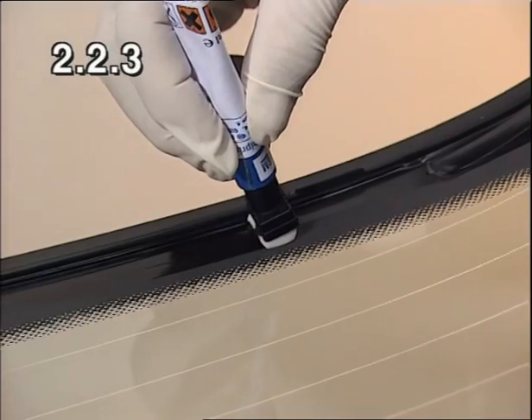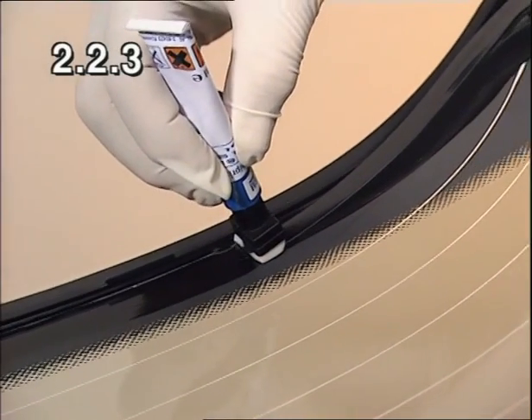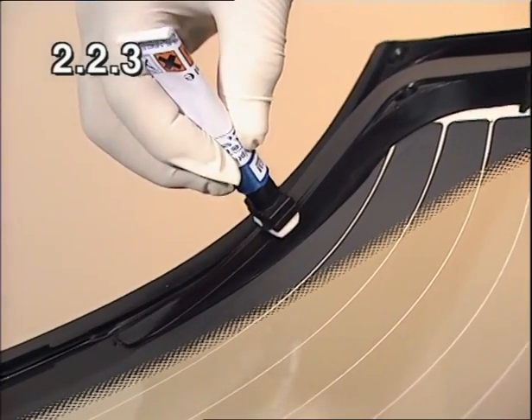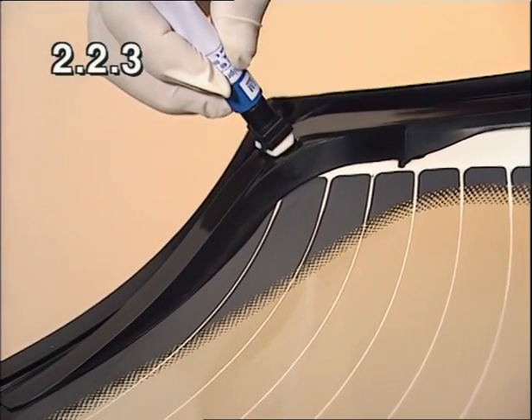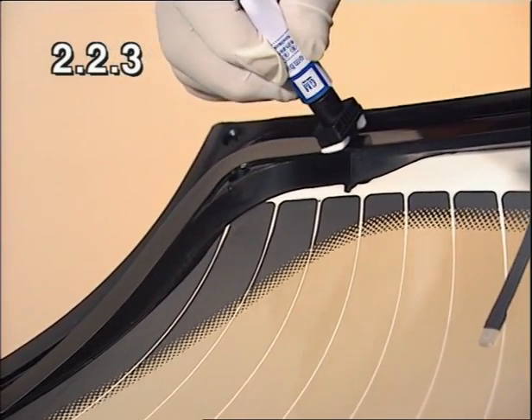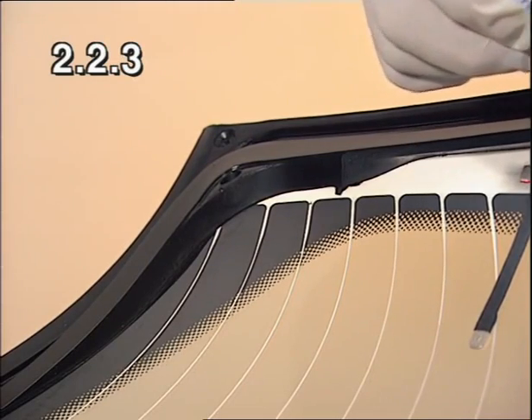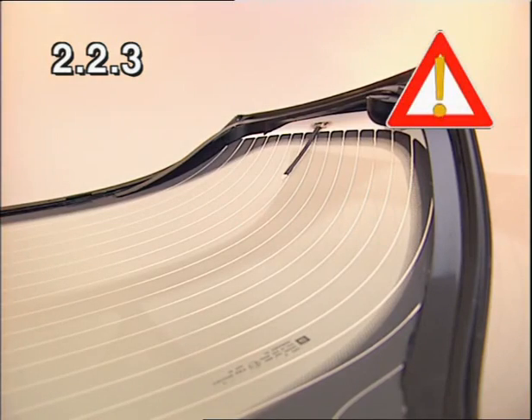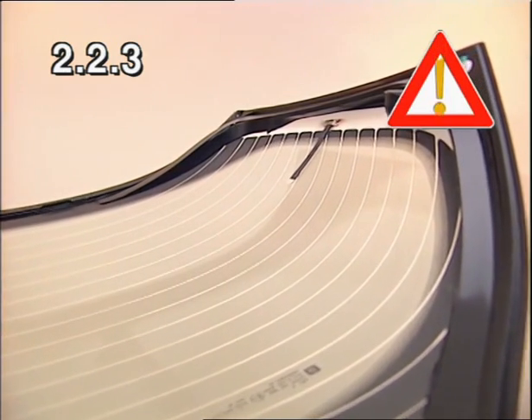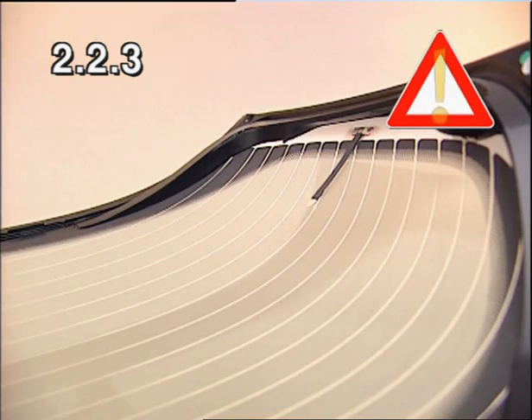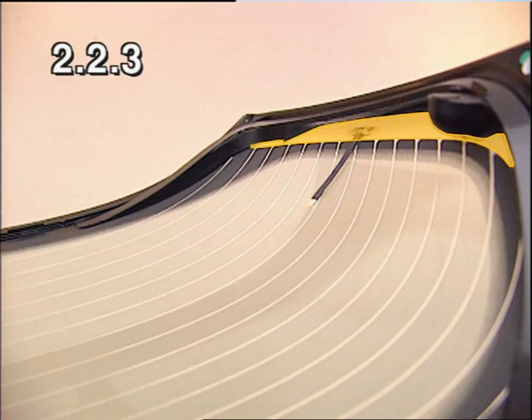In the case of windows with a sprayed-on PUR rim, such as the tailgate window of the Signum, for example, the combi primer is applied in one process to the glass ceramics and to the PUR rim. Caution: when installing windows with heating conductors, there must be no contact between the adhesive and the collecting rail of the heating conductor. At this point, electrical transfers are possible, which can lead to corrosion damage to the body frame, even though the adhesives used in production and service consist of a PU material with low conductivity.